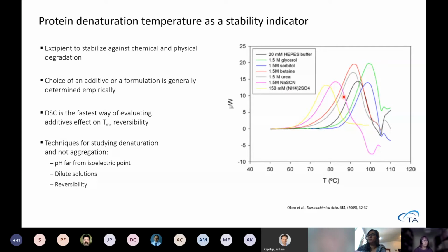So it's a quick way of screening, but note also here that these are now denaturation, it's endothermic. After denaturation, some go exothermic down, which means they start to aggregate. So we can see the yellow one looks less stable than the pink one. We can see that the yellow one doesn't aggregate afterwards, while the pink one is aggregating afterwards, meaning that we are driving the equilibrium to aggregation.